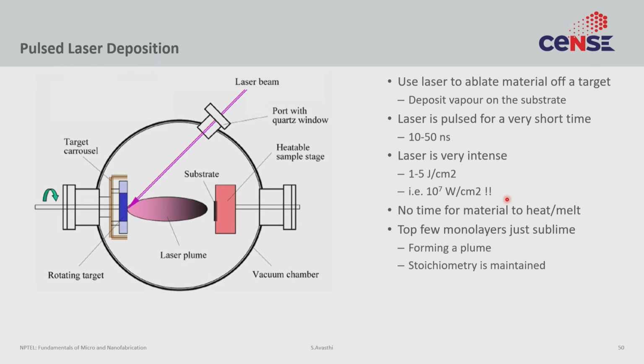But the things to notice here are that the laser tends to be very intense. So the intensity of the laser tends to be in joules per centimeter squared, which is a very high amount of power in a very small area. Also, scale-up is a little bit of an issue. Even commercially, very few tools are available that can do uniform deposition over 6 inches. So that's a challenge. It's still an R&D tool, not so much a commercial tool.